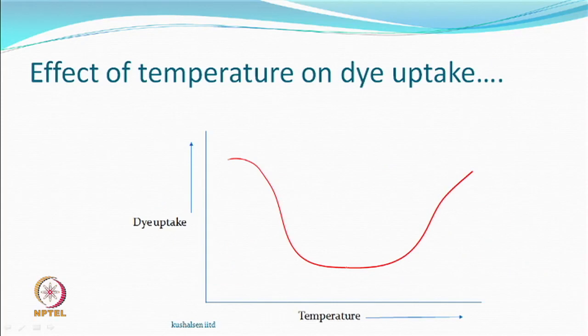After some discussion we came to a state where we said the dye uptake initially decreases because the crystallinity is increasing and the dye can go only in the amorphous region. But thereafter it again starts increasing, and we left it at this point saying that maybe you would like to say something on it.